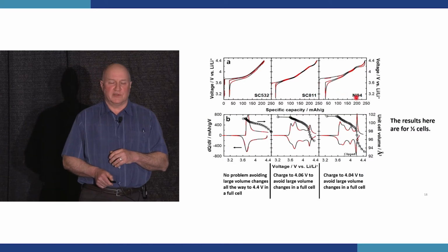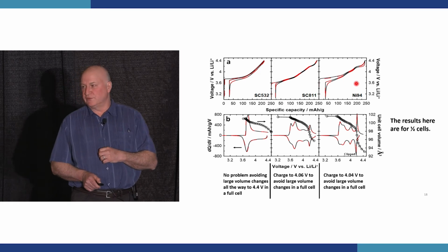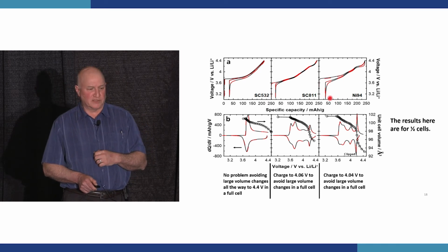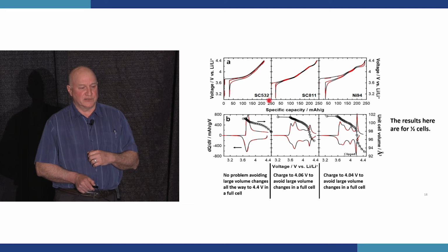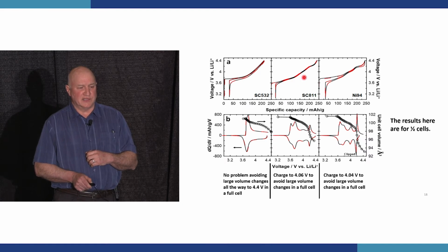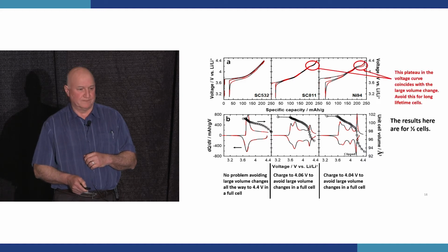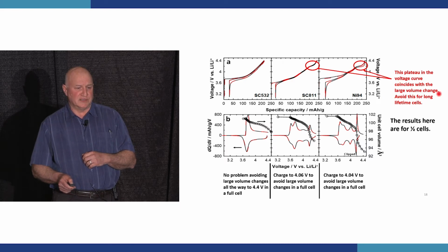All right, so I want to talk now about the importance of avoiding large volume changes. So here I show data for NMC 532, voltage versus specific capacity, and NMC 811, and a material that has 94% nickel. And you'll see the nickel 94 and the 811, they have a plateau here around 4.2 volts. And this plateau in the voltage curve coincides with a large volume change in the material.